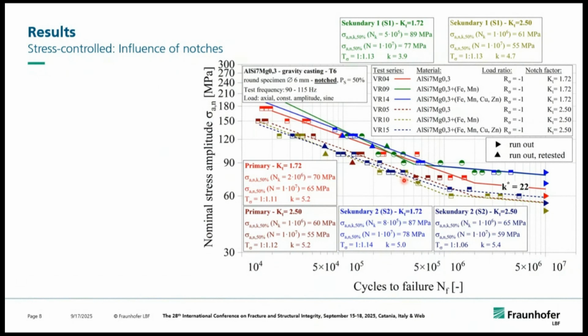What is remarkable is that the scatter bands are comparably low. Okay, we did not test 50 specimens for each SN curve, but nonetheless, we see that the different scatter bands that we derived here are comparably low, especially when we keep in mind that usually for a cast material, we would tend to have something like a T sigma of 1 to 1.3. There we have really good results in this case.